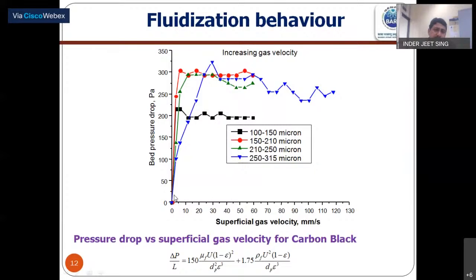So this is a typical plot of a fluidized bed where, for various dimensions of the carbon black, we found the minimum fluidization velocity, where the bed pressure drop doesn't increase. There is a famous equation, the Ergun equation, from which we can theoretically calculate the minimum fluidization velocity, but practically and experimentally we can find it by this pressure drop measurement.